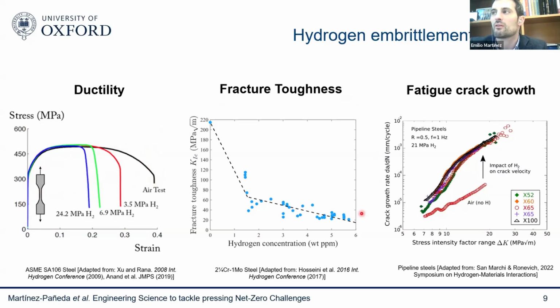And the effect is even more remarkable if you talk about fracture toughness. Again, those of you who did your undergrad here will remember those concepts from first year and second year statics and structures courses. We talk about fracture mechanics, fracture toughness. This is the resistance of a material to fracture. You can see that this is a pressure vessel steel, and it goes all the way from a fracture toughness of 220 megapascal square root meter to well below 20 megapascal square root meter. And you can see that the quantity of hydrogen here is 6 parts per million. A tiny amount of hydrogen can reduce the fracture resistance of a metal by an order of magnitude. So basically, you go from something that is very ductile, that you really want to use for your structures, to something that is almost as brittle as an engineering ceramic. So this is a problem, of course.